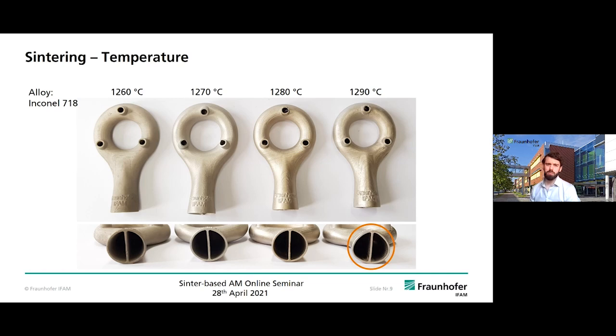So at 1290 degrees there was approximately 40% of liquid phase, and this was too much for this part to maintain its shape. So for 718, we normally use temperatures between 1260 and 1280 degrees.